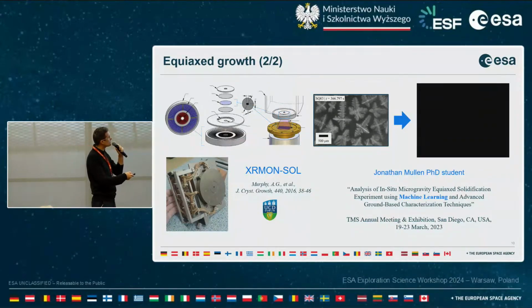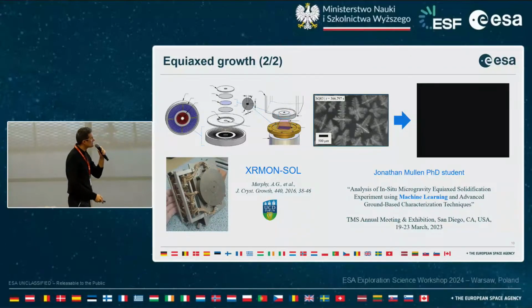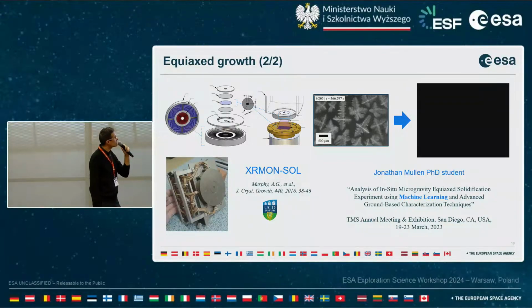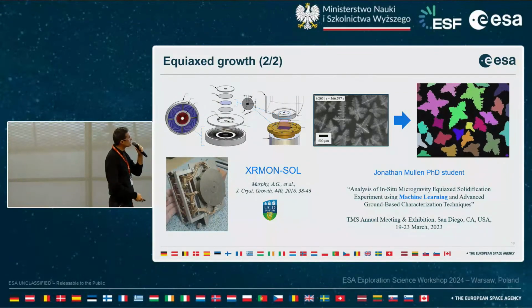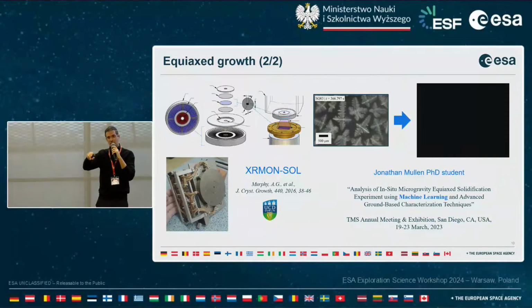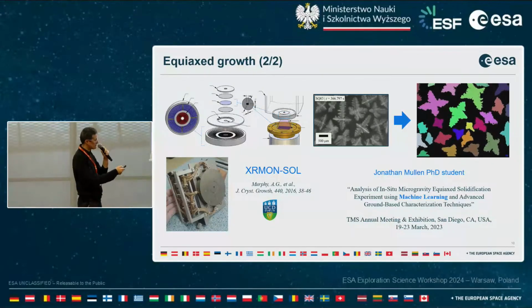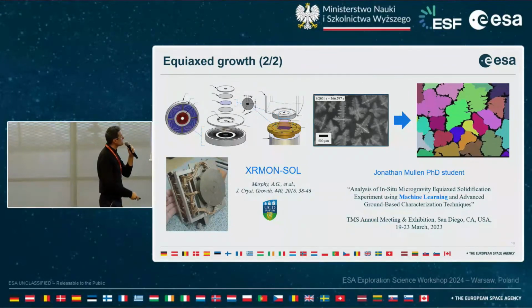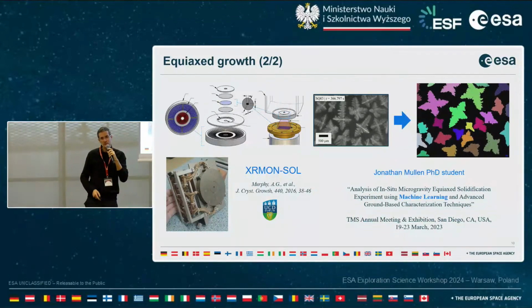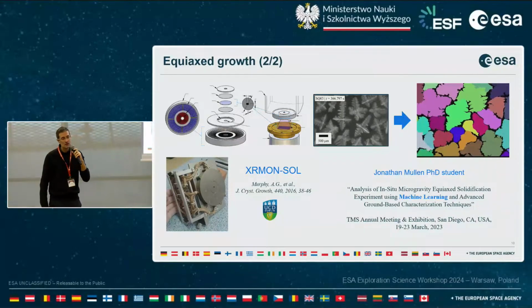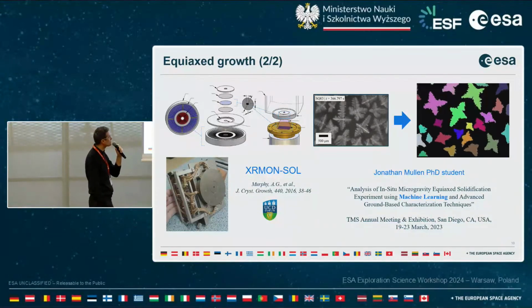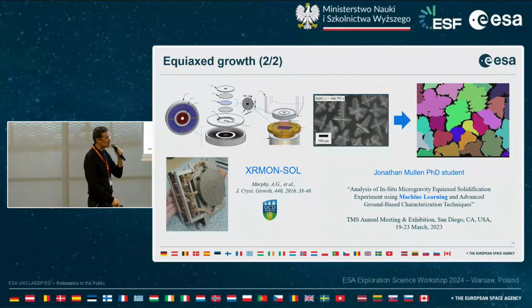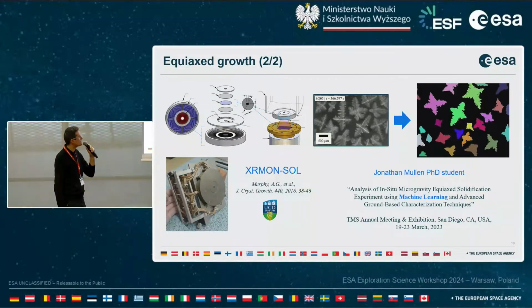And what is interesting currently is that the UCD group, during the PhD of Jonathan Mullen, is actually applying machine learning to try to study the nucleation of each individual grain. And this gives this kind of very nice videos where you can see that the software identifies each grain separately, and it is then possible to follow the development of each grain. And this segmentation process is actually not so easy when using a conventional algorithm, and the use of machine learning in this case has been very successful, and our colleagues at UCD are keen on sharing this algorithm to apply it to other experiments.